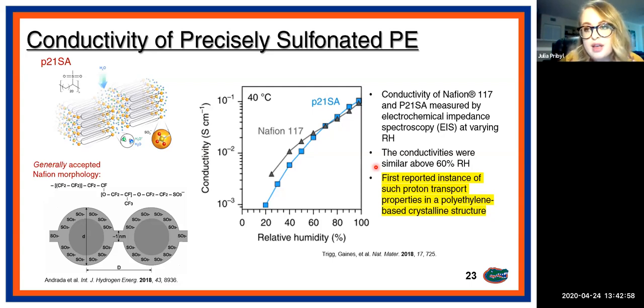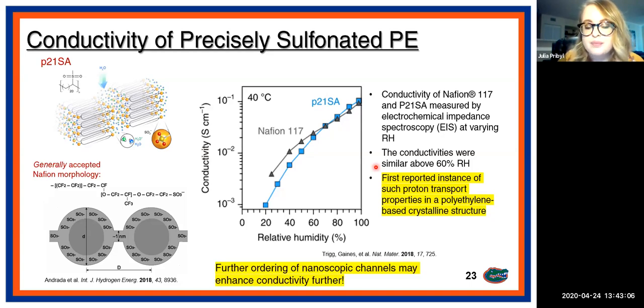One thing to note about this work is that the direction of the channels was not biased in any way. So this was just simply a melt crystallized sample, and modeling studies from this work suggested that further ordering of the nanoscopic channels may further enhance the conductivity by decreasing the tortuosity that the ions have to go through to reach the other side of the membrane.